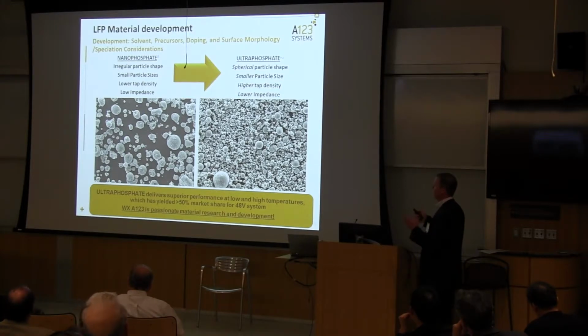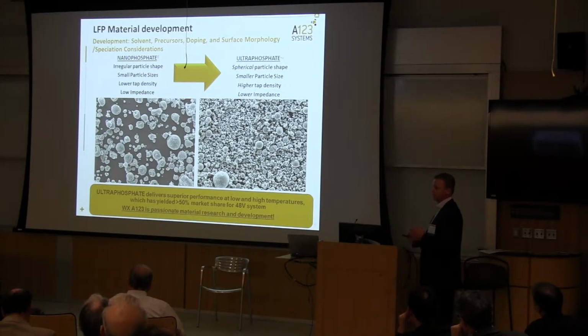So we went back all the way to the beginning and looked at actually the morphology and the structure of the precursors. So the development strategy on going from the nanophosphate, which the last version of that was our Gen 3.5, all the way to our first version of our ultraphosphate, our Gen 4, is we looked at the solvents that we did for our slurries, because that had an impact on the morphology, both on the primary and secondary particle structure. The precursors are key.